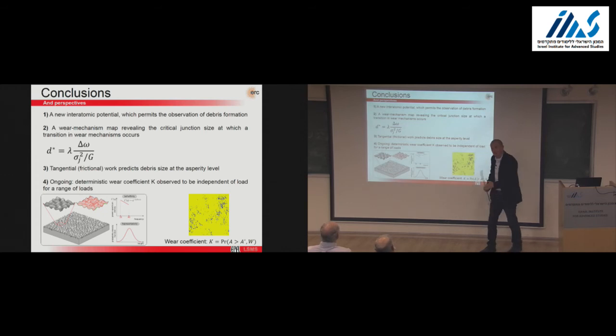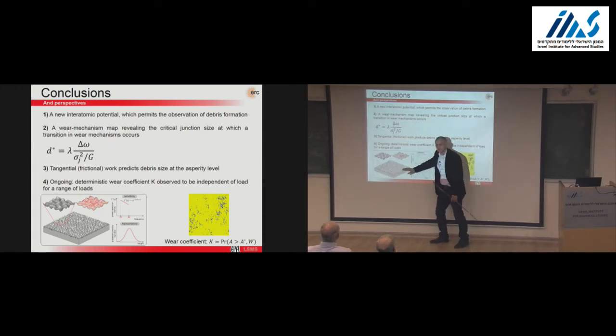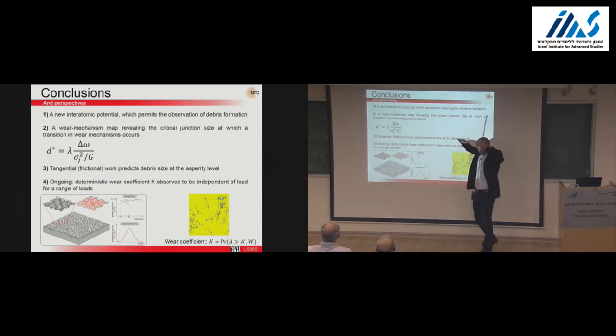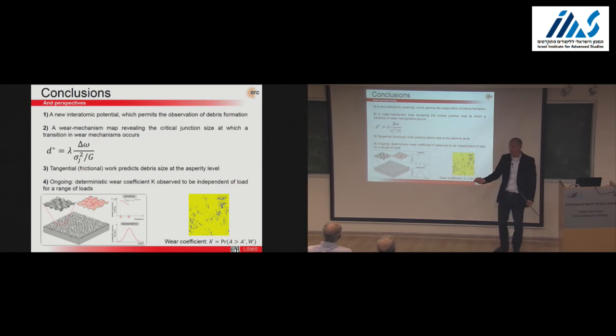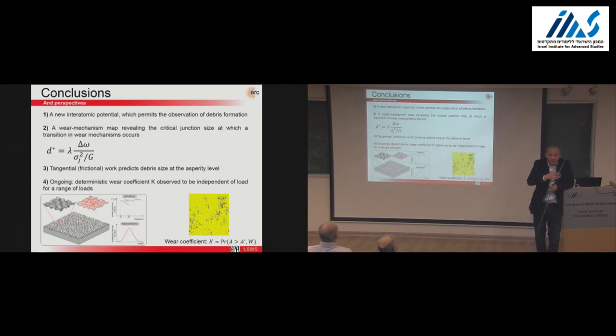And what we're trying to do, I'm not going to show this today, but we are doing mesoscale calculations, so boundary element method type calculations where we have large representative surfaces with lots of asperities at different length scales. And we can compute the distributions of contacts, of microcontact sizes. So we have statistics on this. And then we can just count, right? Count how many of them are above a critical size and come up with an estimate of K.